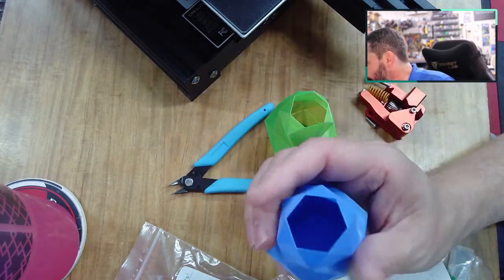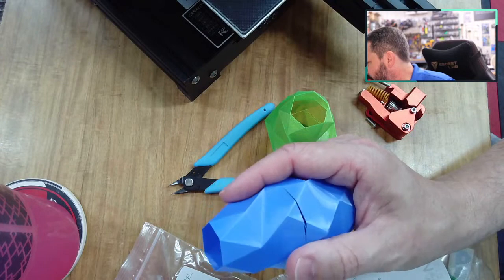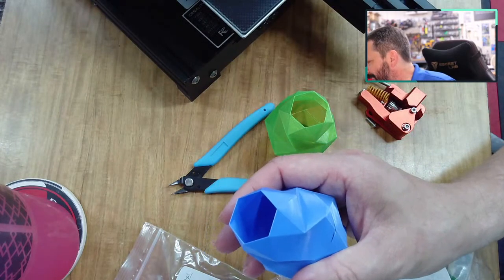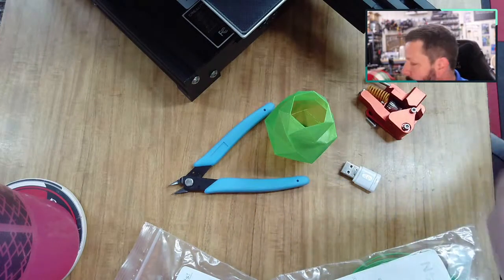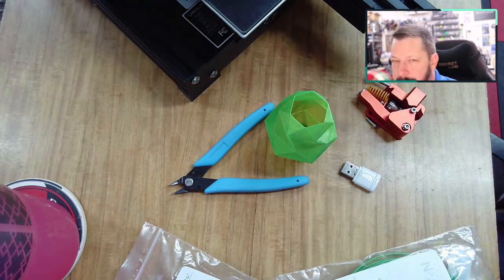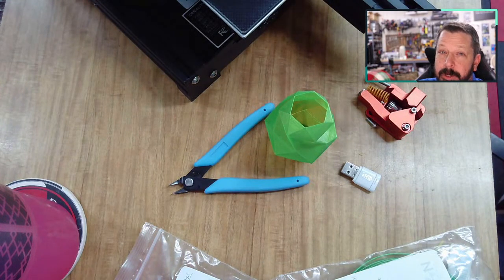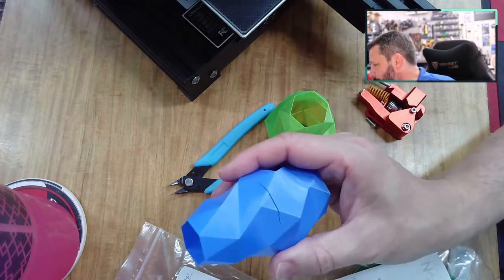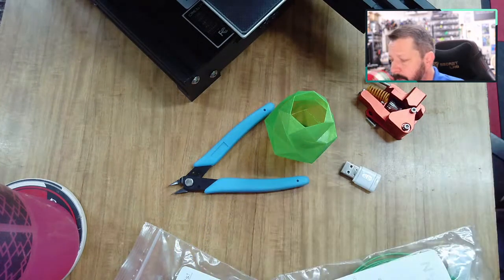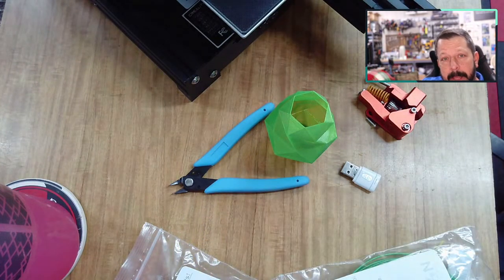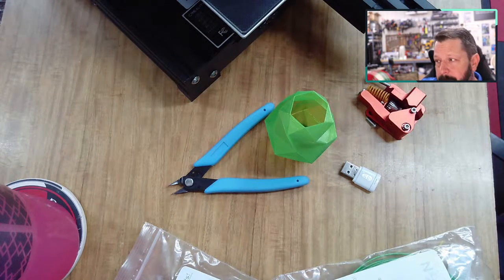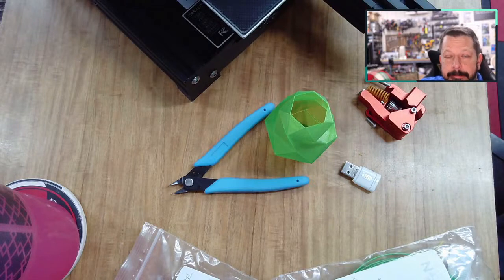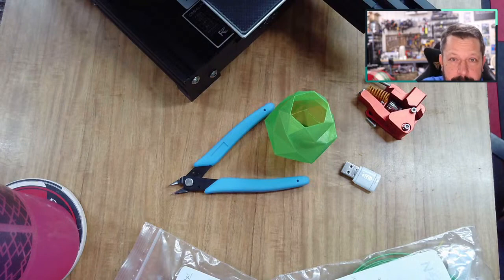Now these, I'm pretty sure if I apply, since they have such bad layer adhesion here, see, it's cracking. I can't do much, but it's because the layers are coming apart. They're just not welded together well enough. So that's a problem with that, but I think that's more flow rate, and I might have been printing a little bit on the cold side. So if you get this to happen, your parts are just not holding together. Flow rate could be one issue, and too low of temperature. So it's able to extrude the filament, but it doesn't actually extrude enough of it. Or it's too cold and it's printing, but the layers are not bonding together very well.